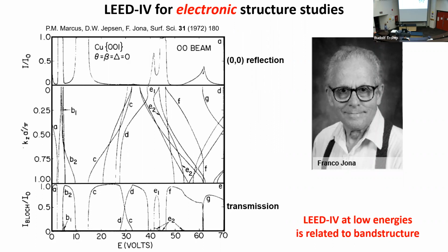Why is that? Well, it is because we have a huge band gap here. You see in this region here, there are no states in the band structure. If there's no chairs to sit on, right, you've got to stand. So if there's no place for these electrons to live, they cannot enter the solid. They must come back, right? And so here we see already in 1972, by this, at that time, a relatively straightforward calculation, that the reflected electron intensity in this simple case is directly related to the unoccupied band structure.